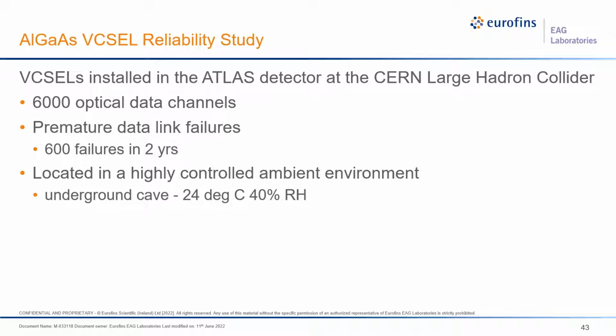Now, these VCSELs were installed in the ATLAS detector at the CERN Large Hadron Collider. They have 6,000 optical data channels in this detector, and they were having premature data link failures. That's 600 failures in 2 years. And this is a problem because the detector is located in an unusual place, in an underground cave that's kept at 24 degrees C and 40% relative humidity.